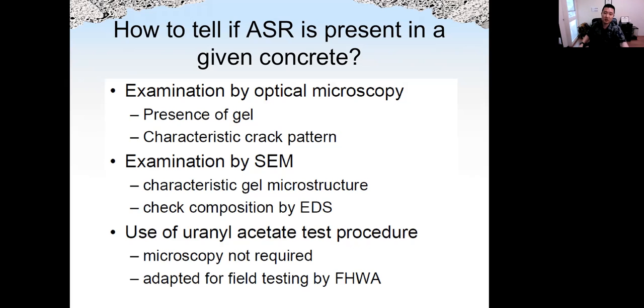We can also use a scanning electron microscope to see the microstructure of the gel, or we can check the chemical composition by EDS. EDS is one part of the test in a scanning electron microscope. It can detect certain types of chemicals in the materials. And we could also use the uranyl acetate test procedure. This is a very simple standard testing method by the Federal Highway Administration. It does not need any microscope. We're going to talk about the procedure, how to use uranyl acetate to see ASR in concrete, in a moment.